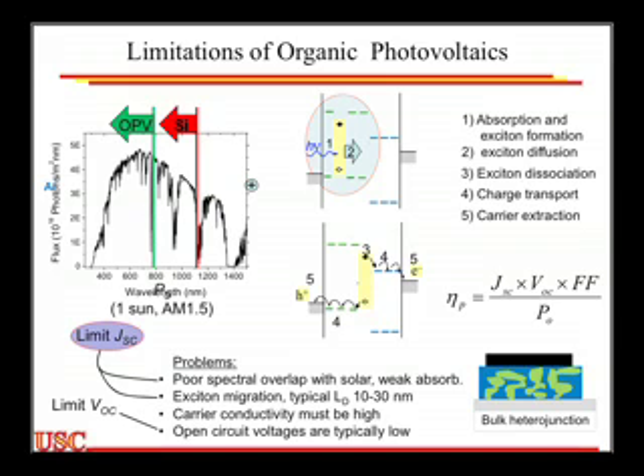So how well do organics do? Well, most of the organic solar cells that you're going to find out there are absorbing at around 800 nanometers and lower. They don't go much beyond about 800 nanometers. Silicon goes out to about 1100 nanometers, 1.1 eV, and so that whole gray area is not being used. So you can imagine if I look at my solar cells, and remember everything relaxes down to this energy, this integrated area is what I'm not collecting in my organic solar cells. And so there's a huge loss.